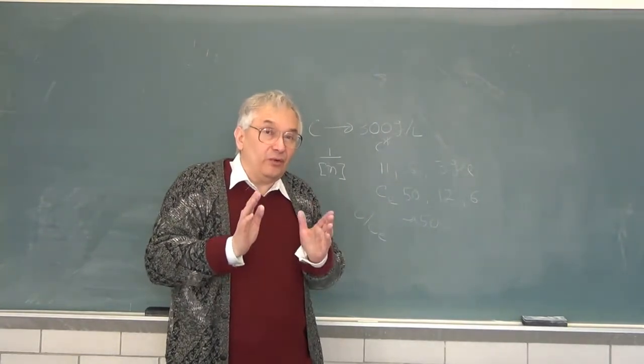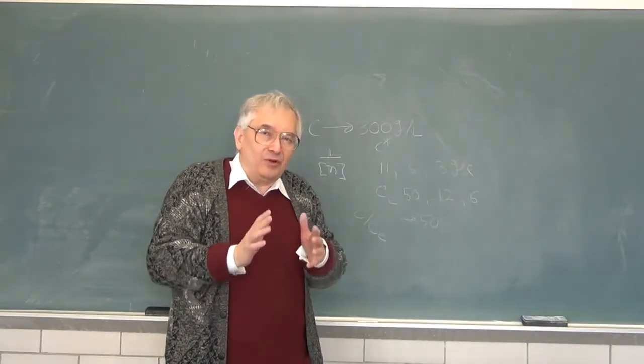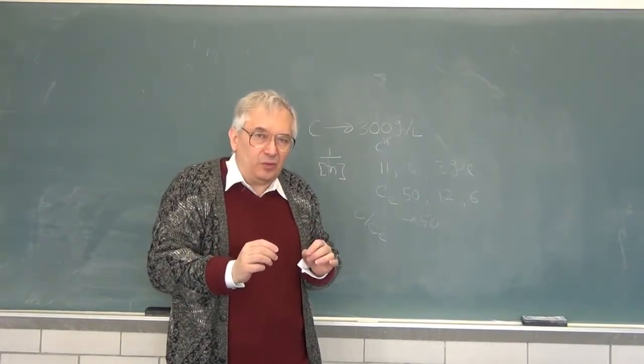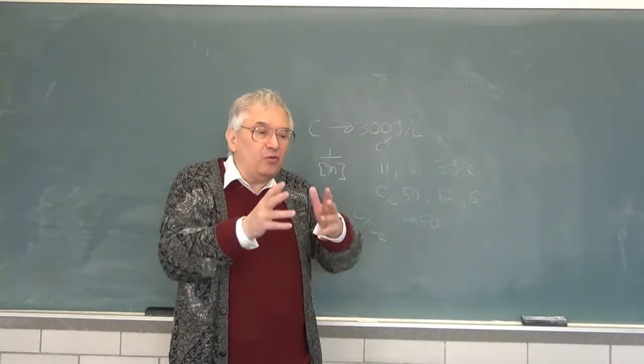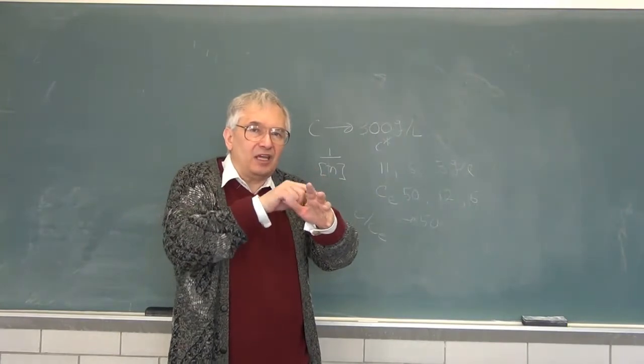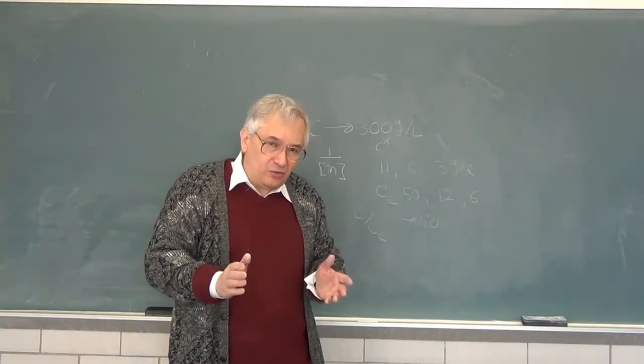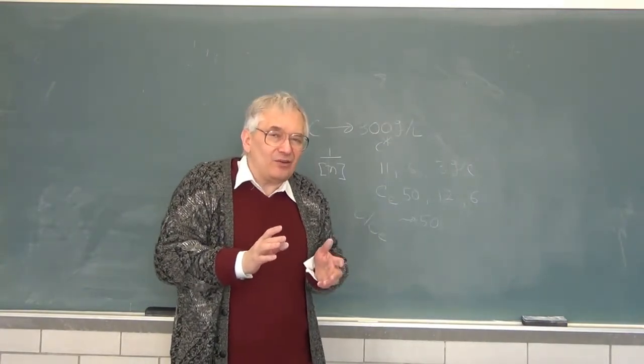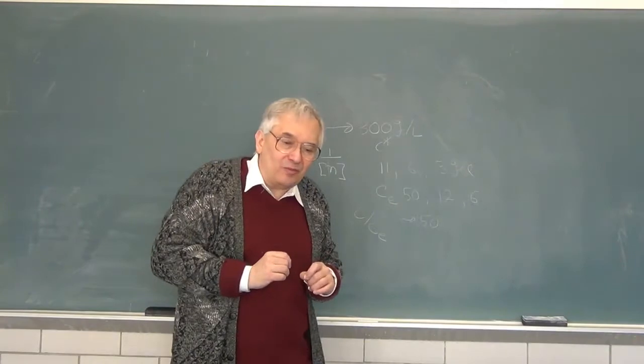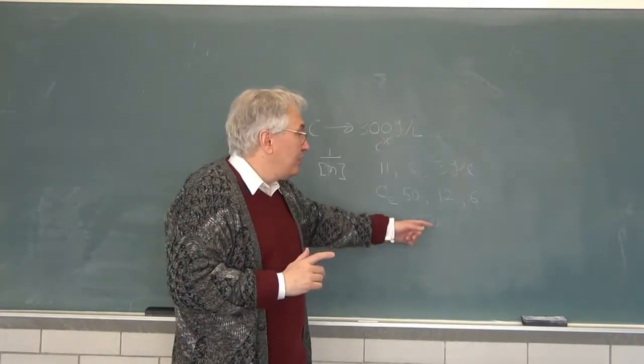Oh, I should pause. I am aware of one model analysis which does predict the sharpness of this transition. The prediction is based, in essence, on the assertion that this entanglement transition, chains all getting entangled with each other, is a percolation transition. That is, you move from chains that are unattached to chains that have entanglements. So you could walk along a chain, hop at an entanglement, walk along a chain, and cover the system. Percolation transitions are extremely sharp, at least usually. However, there are people who don't agree that's how you should analyze it. I just bring it up that there is this range of opinions on what the transition should look like, and at least some of them say sharp and some say otherwise. It doesn't matter here. We clearly got way above the transition. Okay, so that was what was done.